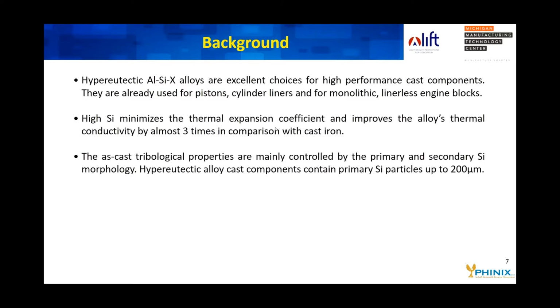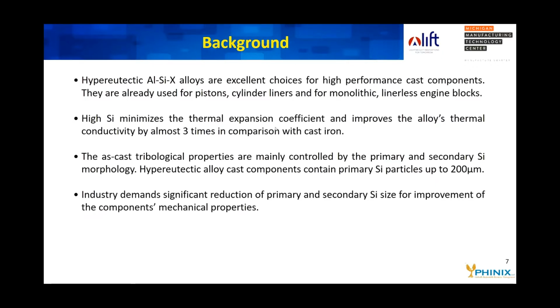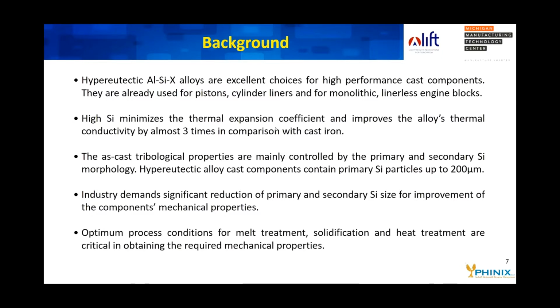As-cast tribological properties are mainly controlled by primary and secondary silicon morphology, but the hypereutectic cast components on the market now contain primary particles of up to 200 microns, and agglomerations of those particles lead to critical flaws that limit their application for strength critical applications. The industry demands significant reduction of primary and secondary silicon size for improvement of the component's mechanical properties. Optimum process conditions for melt treatment, solidification, and heat treatment are critical in obtaining the required mechanical properties.